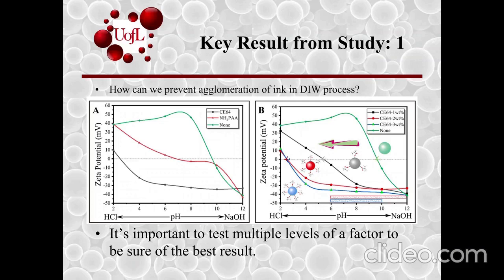Key result 1 from this study. Well, they were addressing the question of how to prevent agglomeration of ink in the DIW process. And so, as I mentioned before, the CE64 was the dispersant, and they tested multiple weight percentages of this CE64 to see at what ranges of pH it would have a stable zeta potential. And they found that the 2% weight percent was the best and most stable option.